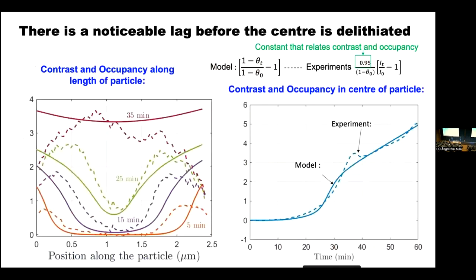Just to think a little bit more about this model, what he was able to show is the modeling of the concentrations versus position in the particle as a function of time. You can see at the beginning of time, you've got a lot of delithiation. It's still pretty lithiated in the center, and then you gradually delithiate the center. If you plot the extent of delithiation at the center of the particle as a function of time, you get this very pronounced phenomenon of a lag, and then suddenly it delithiates. So you have quite a good fit with the experiment.